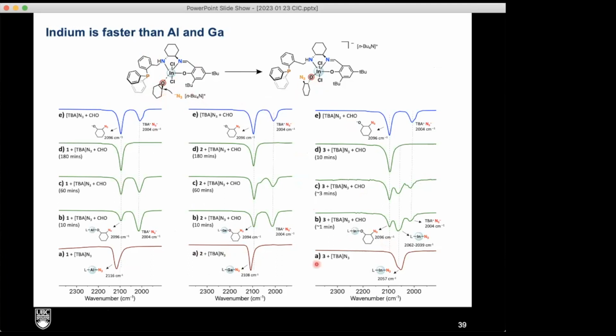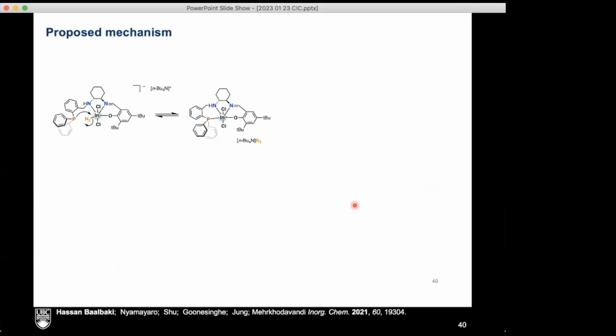And you can see that in the IR spectra. But I want to show you this peak here, which is really important. So this is the formation of this new species here. The same thing happens for all three, aluminum, gallium, and indium. That's the first step. But the difference between them is for these two, it happens in 3 hours. So for aluminum and gallium, this is much slower. For indium, it happens in 10 minutes. So this part of the reaction to me shows you the importance of having that difference in the metal here. This first step happens in 10 minutes for indium versus 3 hours for aluminum and gallium. So